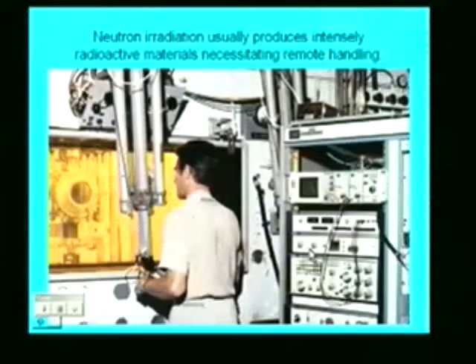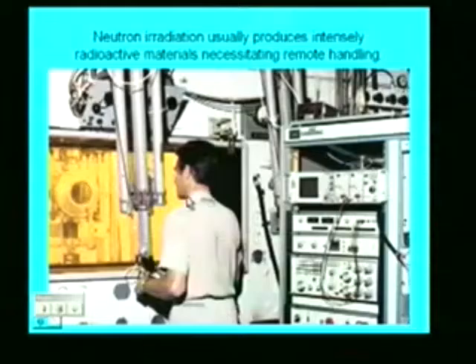Another problem is that neutron radiation usually, in fact most always, produces intensely radioactive materials, which then necessitates remote handling. So when we generated these data, all of these tests were done behind 3 to 5 feet of high-density concrete and maybe 3 feet of lead glass, or a tank filled with, in this case, zinc bromide solution. Then all the materials are handled remotely with manipulators. In this case, we have an ultra-high vacuum chamber that's operated entirely remotely.